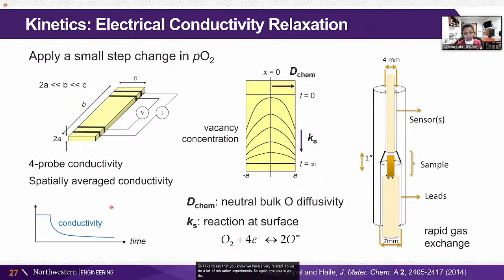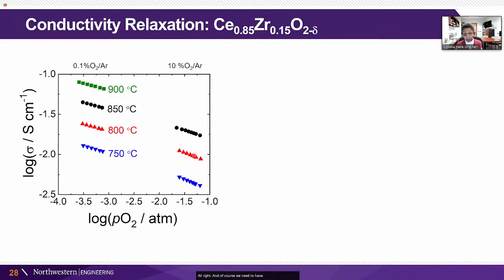So again, the idea is we do a step change in oxygen partial pressure in our chamber. That introduces a change in the vacancy concentration in the bulk material as either it gets oxidized or reduced. And therefore, that changes the conductivity, and we track the rate at which that conductivity changes. It gives us information both on the diffusion coefficient as well as the surface reaction rate constant, because both of these control the rate at which the material relaxes to having the new vacancy concentration. Okay, so we've got a diffusion coefficient that reflects neutral oxygen diffusion through the material, and then a surface reaction rate constant that reflects this oxidation or reduction of the material. All right. And of course, we need to have a material that changes its conductivity with changes in oxygen partial pressure. And so we see that here, and we're studying 15% zirconium doped Ceria.